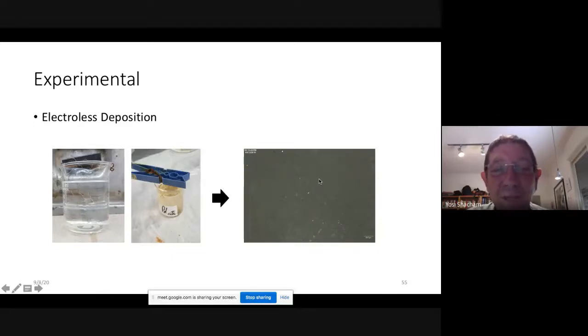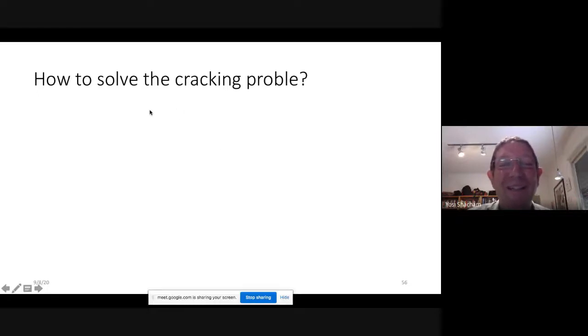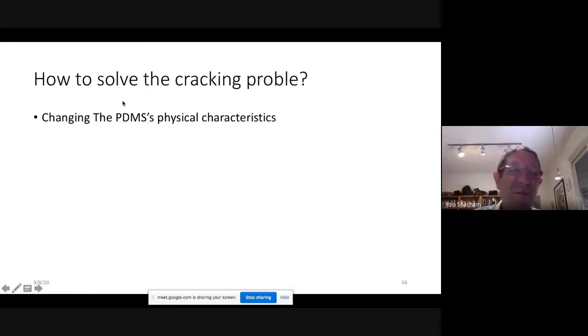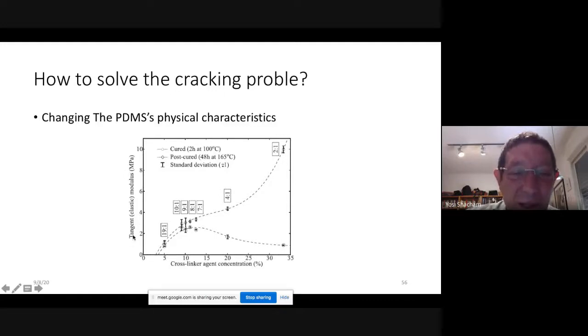But we still want to understand why we get cracks in the old problem, because we really like to do evaporation on plastic because it's really, it's commercial technology. So we looked at the modulus of the polymer as a definition of the crosslinker. Remember, how we make this polymer, we take a crosslinker, mix it with the monomer, heat it, wait. And we look at this table and we saw, well, we can control the Young modulus of the polymer between 1 to 10 megapascal by controlling the crosslinker.